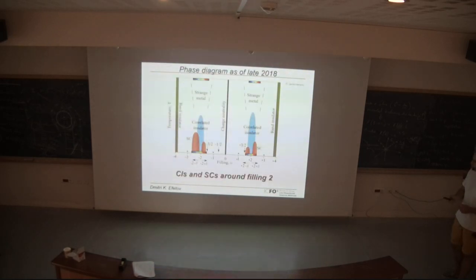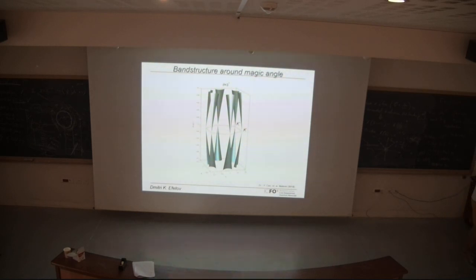Okay, so I also wanted to show this video one more time because I thought it's really interesting. This is again the band structure of twisted bilayer graphene. We start at 3 degrees of misrotation angle, and this band structure at 3 degrees is pretty much the same as what you have for single layer graphene. So again, we have this hexagonal Brillouin zone and these Dirac-like energy bands, whereas we have two valleys, K and K prime, which are equivalent. And even at a 3 degrees angle, these two layers are basically decoupled, and they resemble single layer graphene.